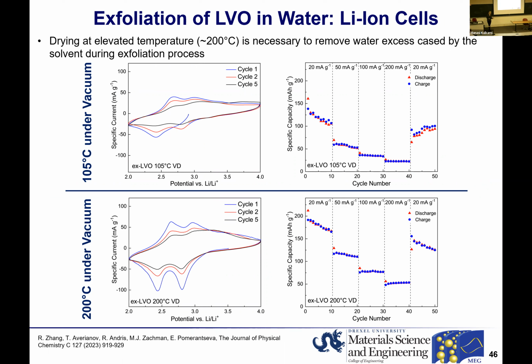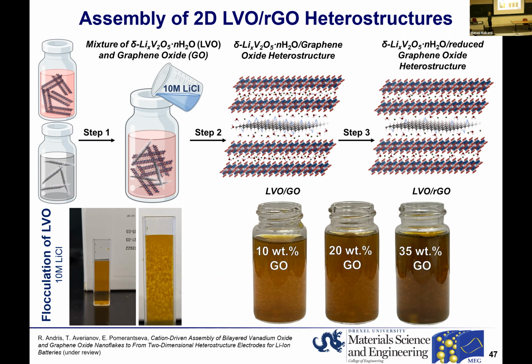And again, just like in the case of the low temperature vacuum annealing, we found that increasing the drying temperature to 200 Celsius gives improvements in electrochemistry. Of course, this is not where we want to be, but this is not the last step, because we don't want to study just the exfoliated bilayered vanadium oxide. We want to make a heterostructure. Another exciting recent discovery that we made is that when exfoliated bilayered vanadium oxide is mixed with graphene oxide nanoflakes in water, we make a much more abundant heterointerface when we use cation-driven assembly.